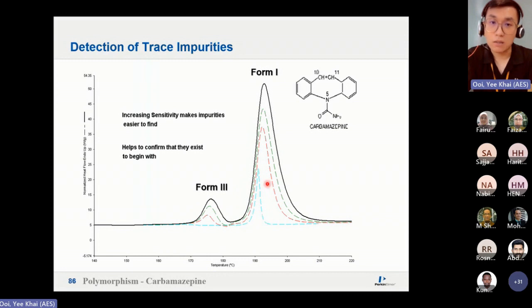But as you heat up with a high heating rate, now form 3 appears. Remember I said the faster you go, the signal will become higher and higher. W equals joules per second, so sensitivity increases. Now they actually found out that the drug exists in form 3 as well, which is not tolerable by the human body. So this is how they confirm for polymorphic materials.